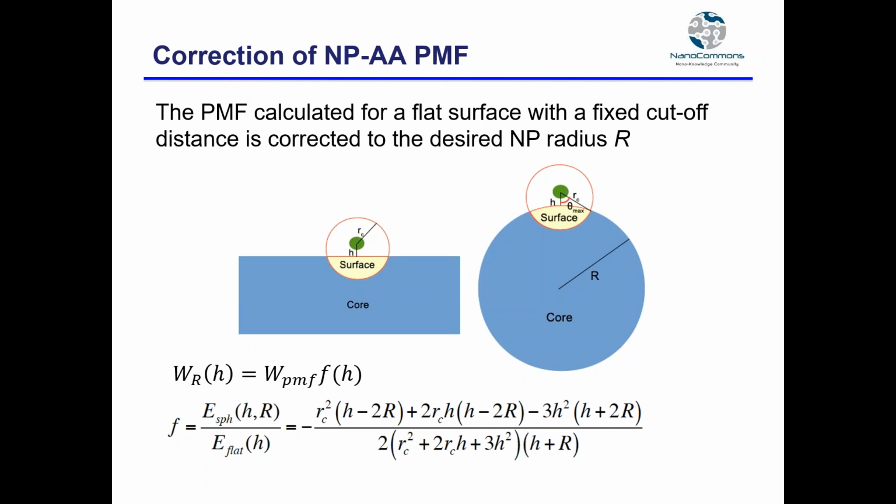The radius can vary from say 2-3 nanometers to 100 nanometers, and the correction formula includes the curvature, so that the actual length of the material that is within the reach of the amino acid is less for a curved particle. But the correction is usually not very large. For the smallest nanoparticles, it may be 20-30% weaker interaction than for a flat surface.